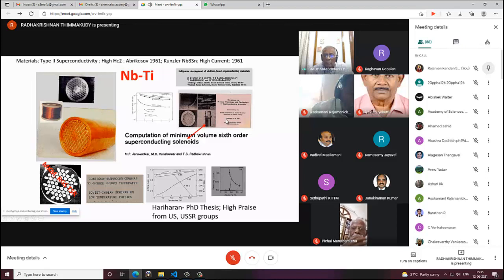this is a resistivity, this is a percentage niobium titanium. I could at will change the resistivity if you only make the material metallurgically unstable. You can see 150 microohm centimeter resistivity has fallen to about 75 microohm centimeter abruptly. So this kind of research was very much appreciated. It's a PhD thesis of one of my students.